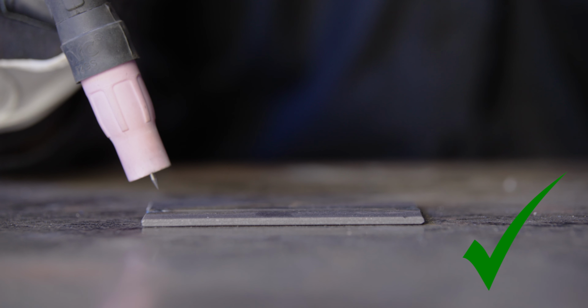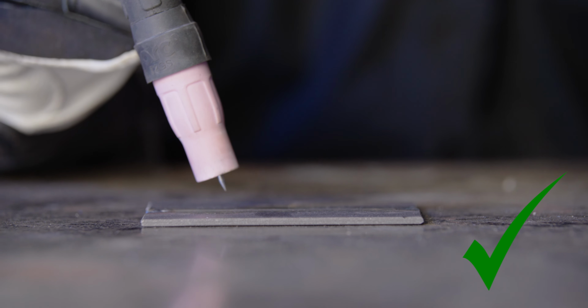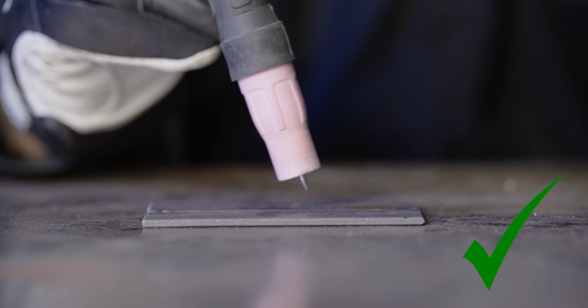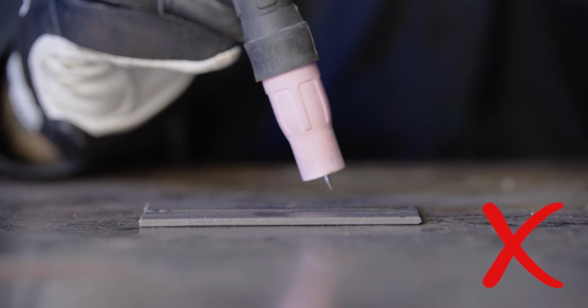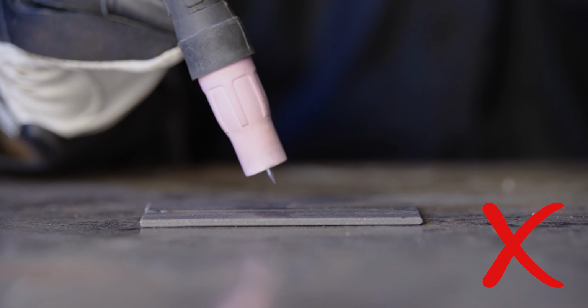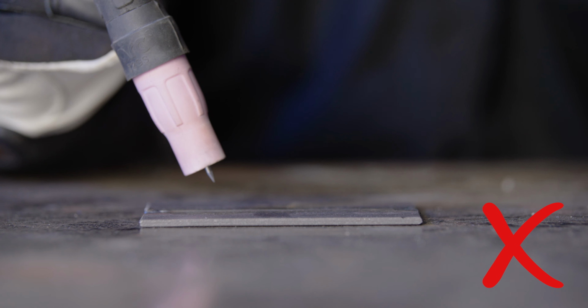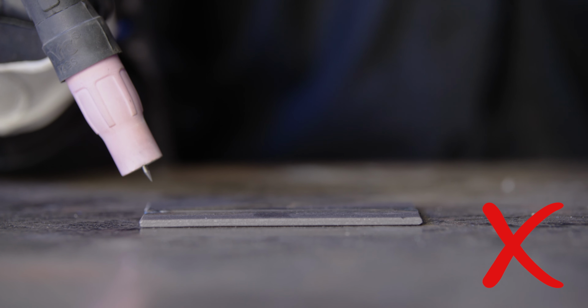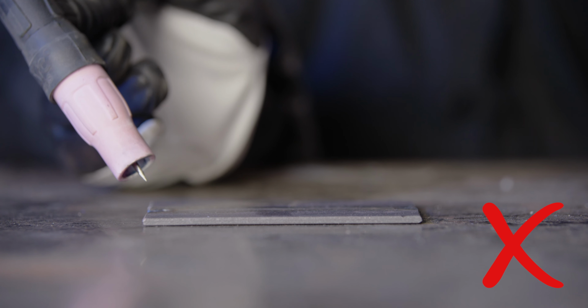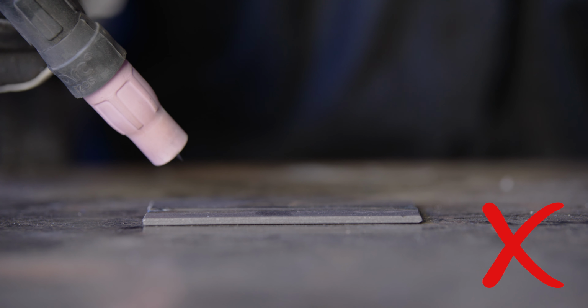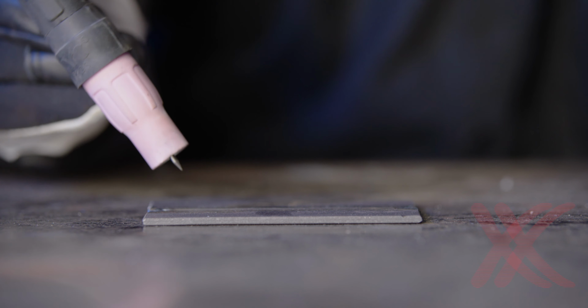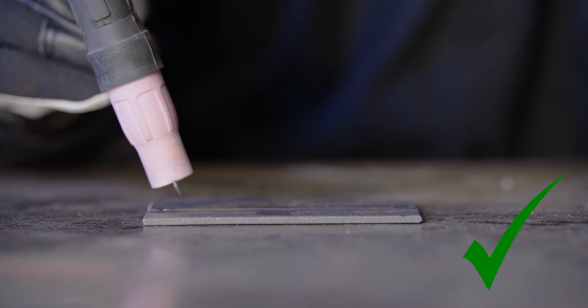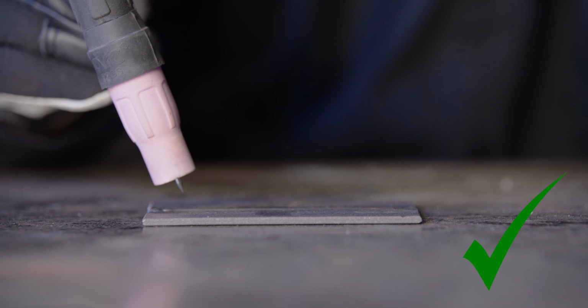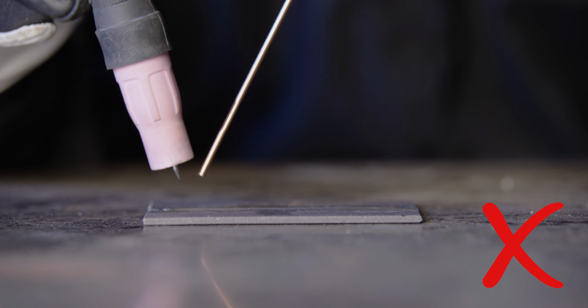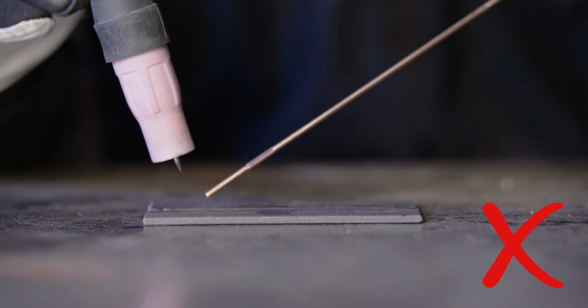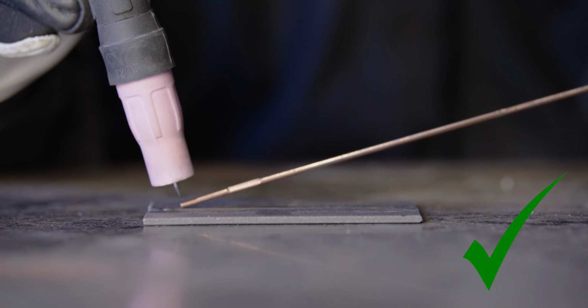A few consistent techniques that will be used for all these positions is that you must always push the torch and not drag it. Dragging or pulling while TIG welding won't penetrate, resulting in porosity in the joint as the gas from the cup won't reach the liquefied metal. You also want to keep your torch at a 10 to 15 degree travel angle as you push on the butt weld, and also the same angle when you're doing a fillet weld for the best gas coverage. Make sure your filler metal comes in relatively low, almost parallel with the joint with a slight 10 to 15 degree angle.